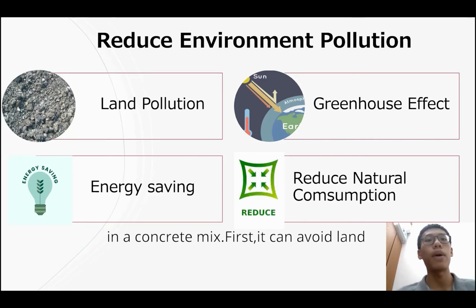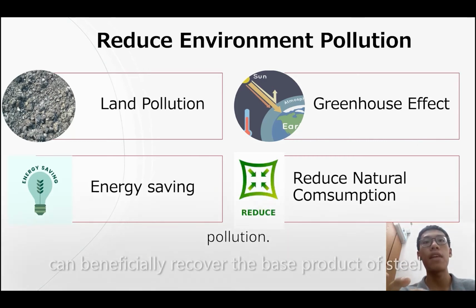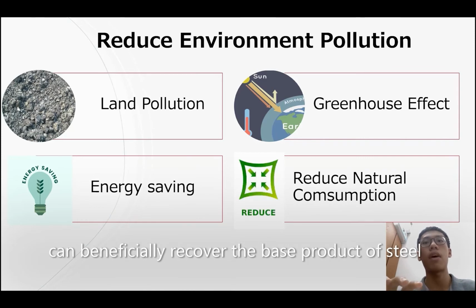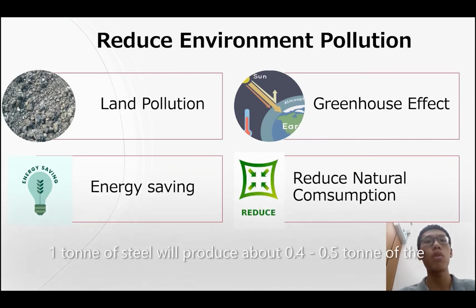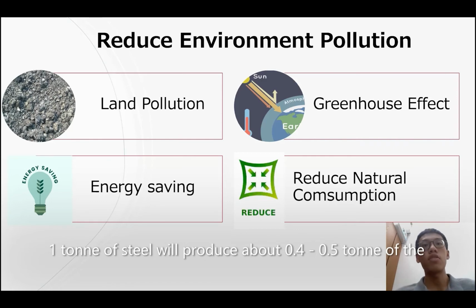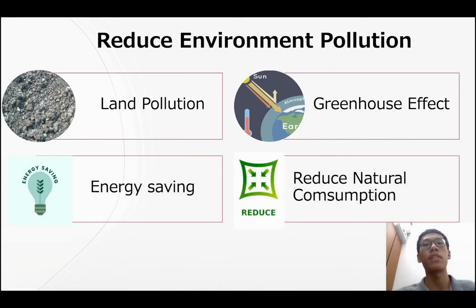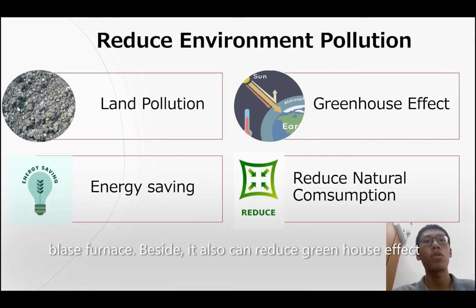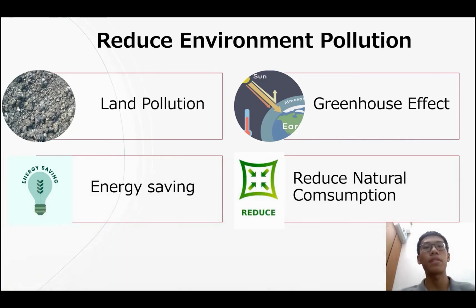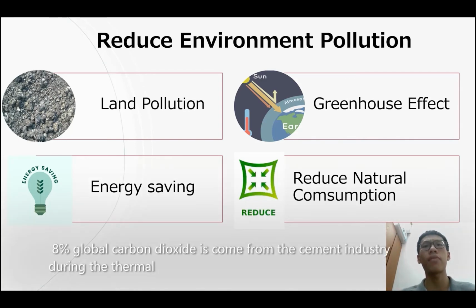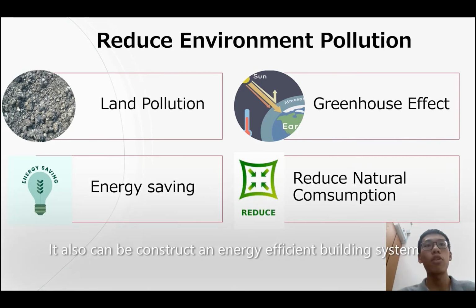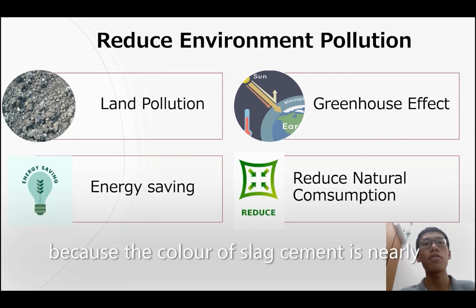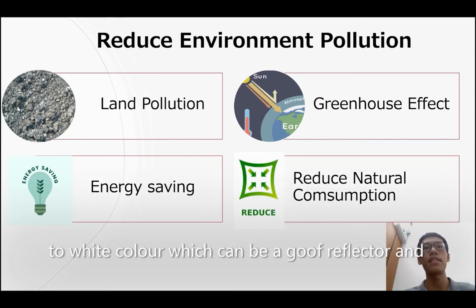First, it can avoid land pollution as it can beneficially recover the by-product of steel, as producing 1 ton of steel will produce about 0.5 ton of blast furnace slag. Besides, it also can reduce greenhouse gas, as 8% of global carbon dioxide comes from the cement industry during thermal combustion. It also can help construct an energy efficient building system because the color of slag cement is nearly white, which can be a good reflector of heat.